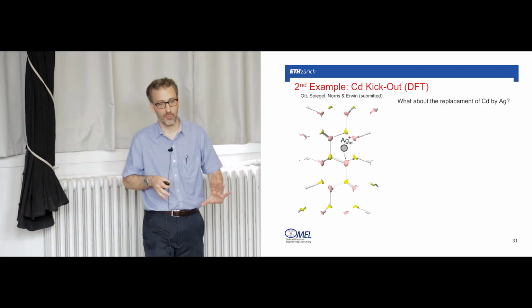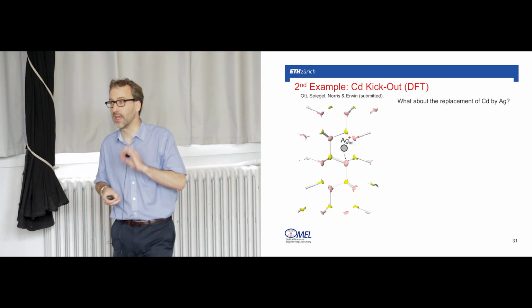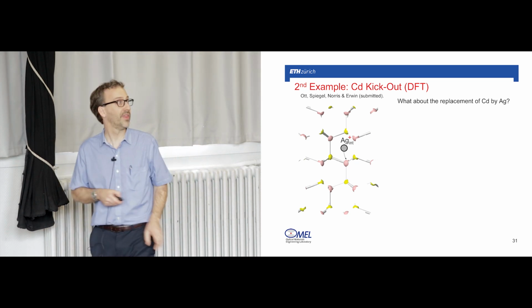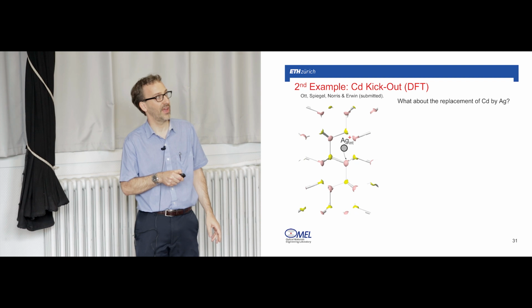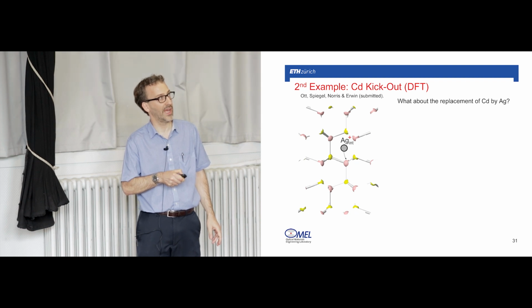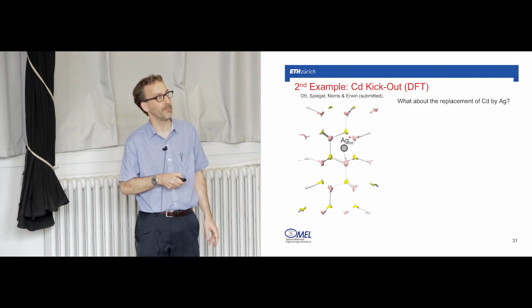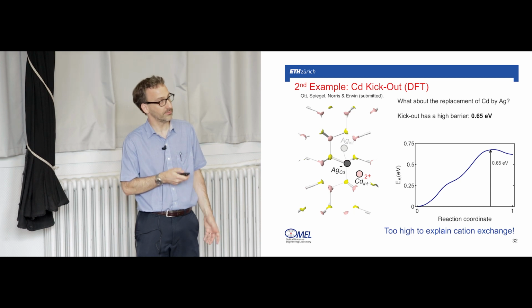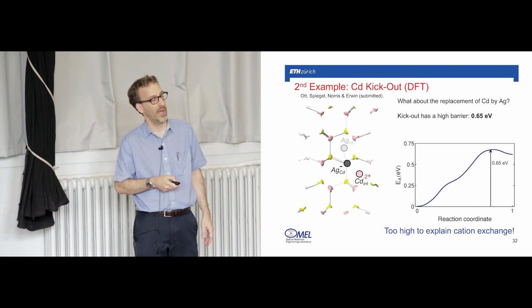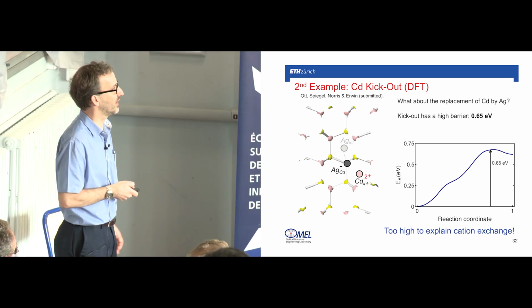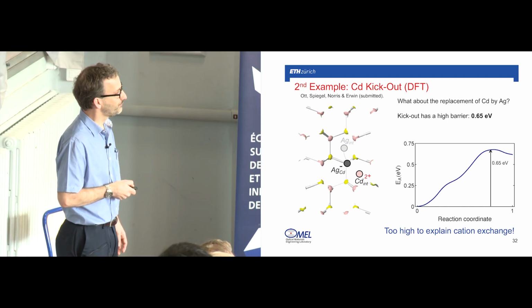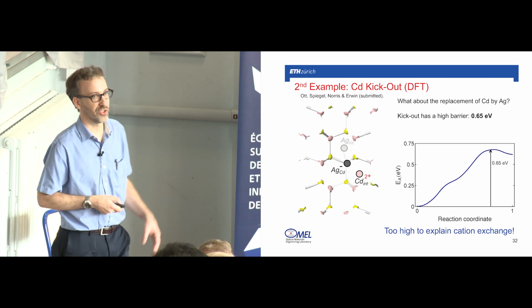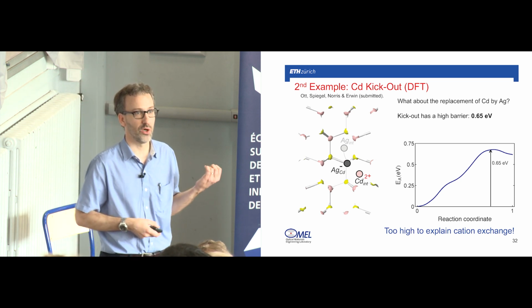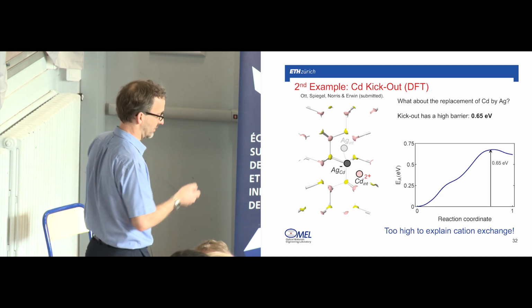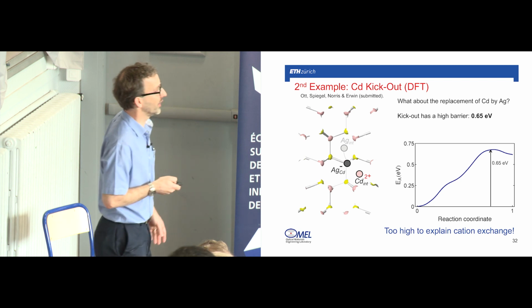And the other important example is that cation exchange will not occur without this reaction. At some point, a fast silver diffuser, an interstitial, has to kick out a cadmium to form a substitutional silver. And if you do the calculations, the barrier of this is enormous. It's 0.65 eV, and this is way too high to explain cation exchange. Cation exchange would be extremely slow if this were the only mechanism going on.